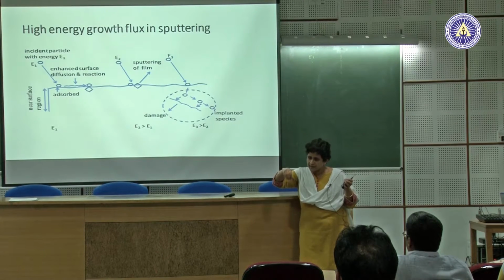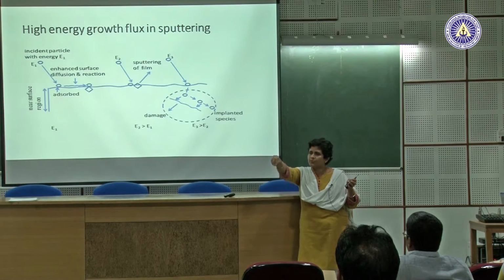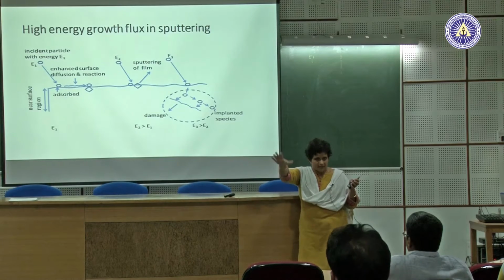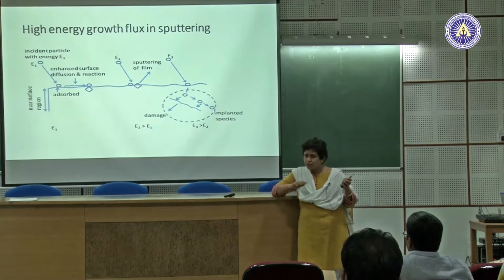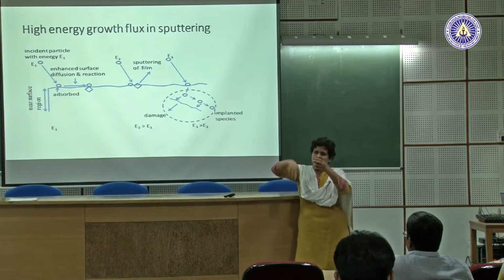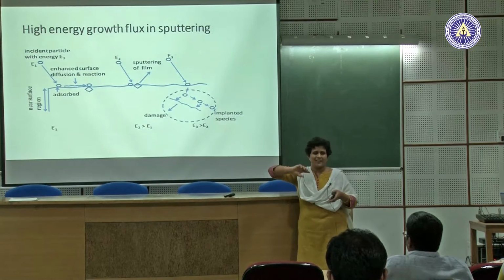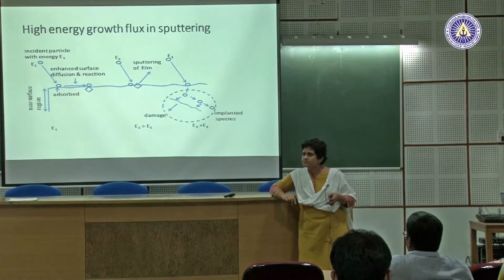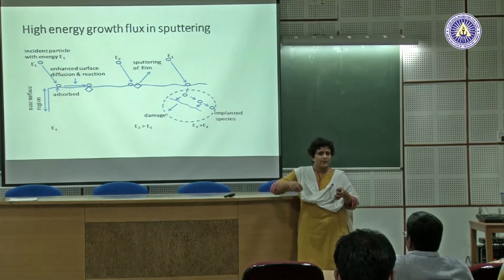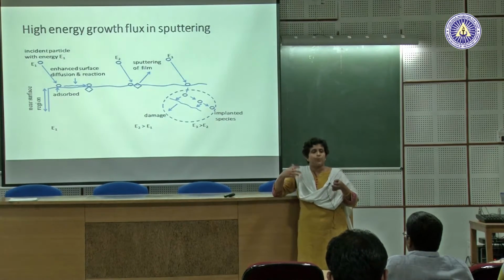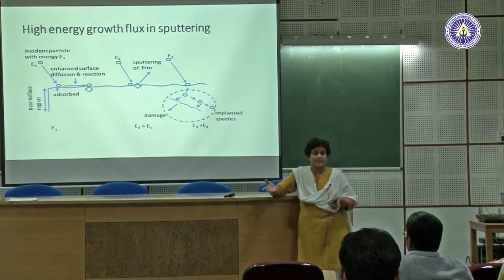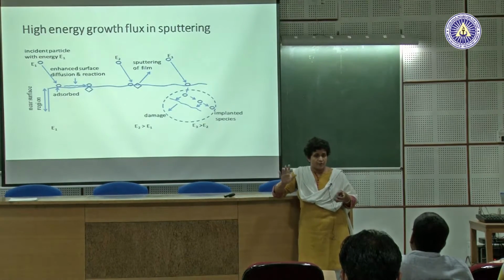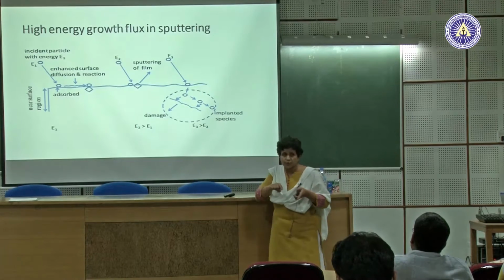So the atom comes, it has enough energy so that it looks around in the vicinity and finds, okay, this is a good place for me to bond to, and it can go to that place and make a good bonding. If you don't allow that process, then they are just coming and hitting and forming a film. It will be a low density amorphous film. But if you allow them to move, then they can nucleate and crystallize. It will be polycrystalline, or even sometimes single crystal films can be deposited. Okay? So this surface diffusion is an extremely important part from the point of view of the kind of film